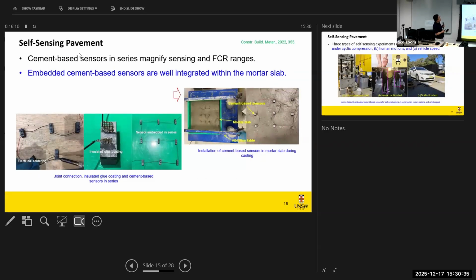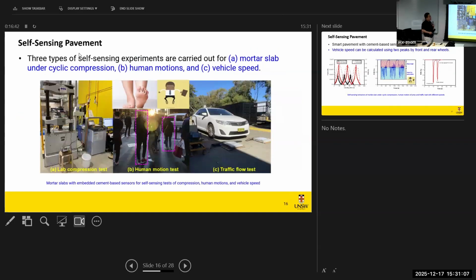Now to exploit the smart infrastructure, here we exploit the piezo-resistive performance of the smart pavement. You can see the cement-based sensors are connected in series to magnify the sensing range and the FCR. The cement-based sensors are well bonded with the mortar slab, to make sure of effective force transmission from the mortar slab to the cement-based sensors. The self-sensing behavior of the mortar slab is analyzed under three types of loading: cyclic compression, detection of human motion, and the calculation of vehicle speed. During the test, a vehicle drives over the pavement, and the data from the cement-based sensors are collected and analyzed at the same time.